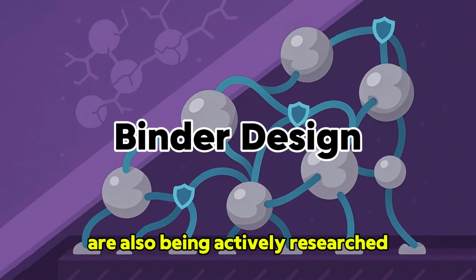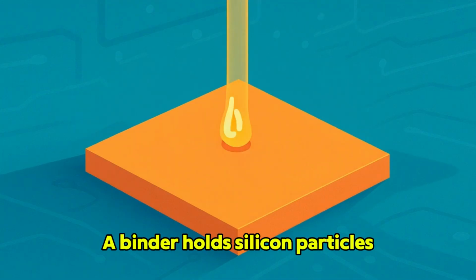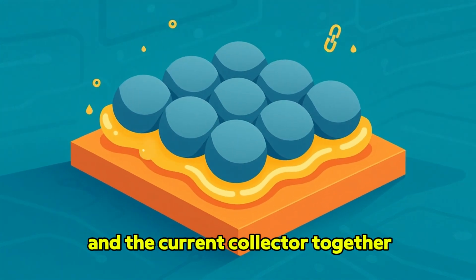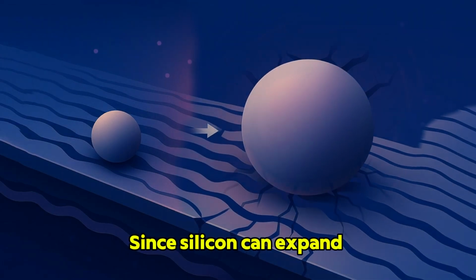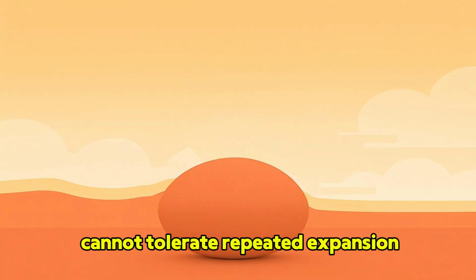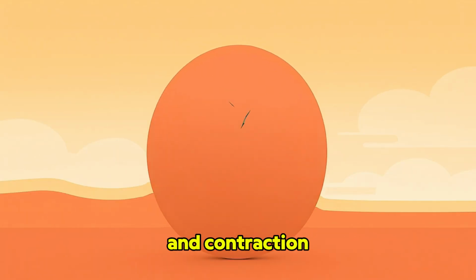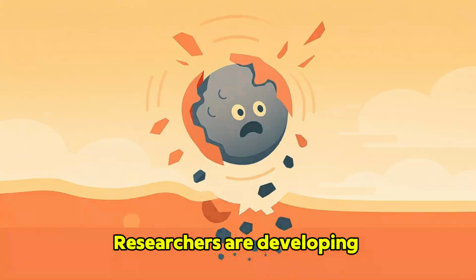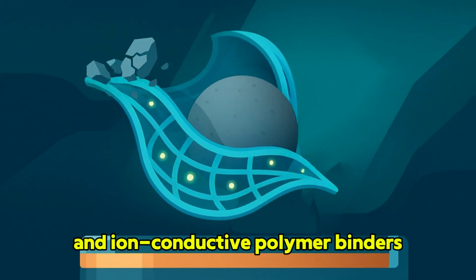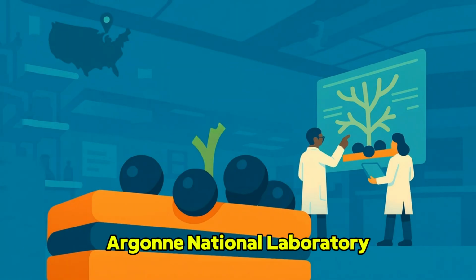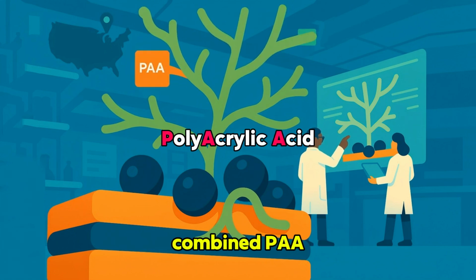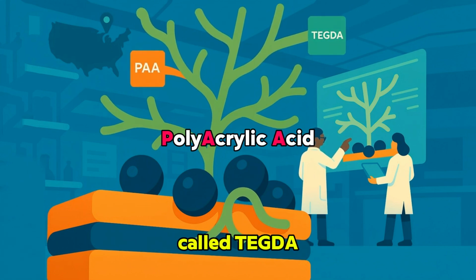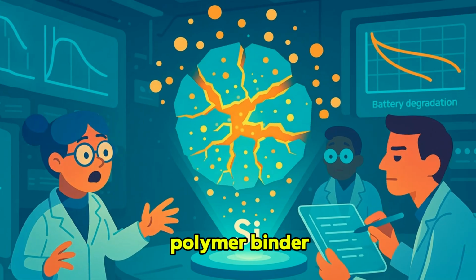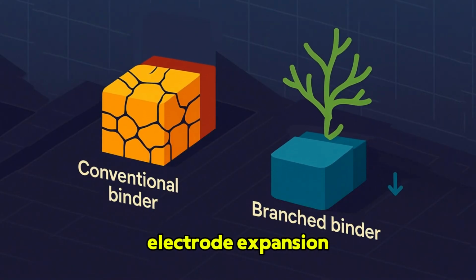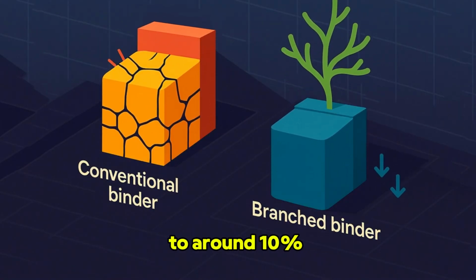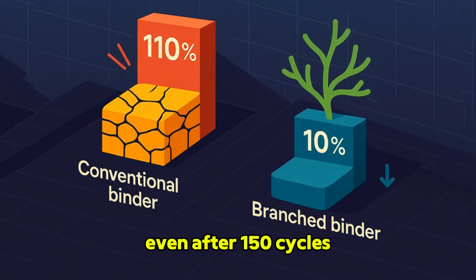Binders that can withstand expansion are also being actively researched. A binder holds silicon particles and the current collector together. Since silicon can expand up to 300%, conventional binders cannot tolerate repeated expansion and contraction, causing electrode damage. Researchers are developing more flexible and ion-conductive polymer binders. For example, Argonne National Laboratory combined PAA with a cross-linking agent called TEGDA to create a new branched polymer binder. This structure reduced electrode expansion from about 110% to around 10% even after 150 cycles.